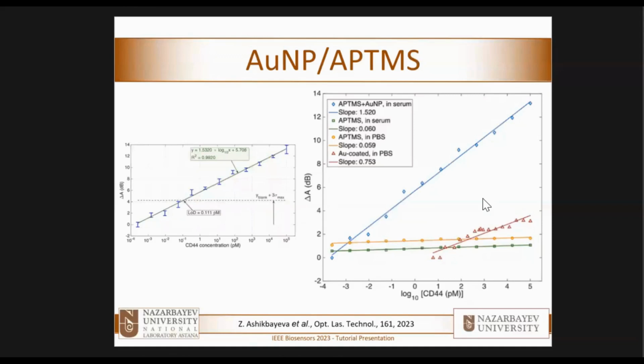And in this case, using again APTMS, but with the addition of gold nanoparticles after the functionalization. So the increase of reflectivity is quite remarkable. It's seen in the spectrum, which is not displayed here, but of course that's quite predictable. What we have also here is that the change of intensity is also quite remarkable. So the sensor is more sensitive.